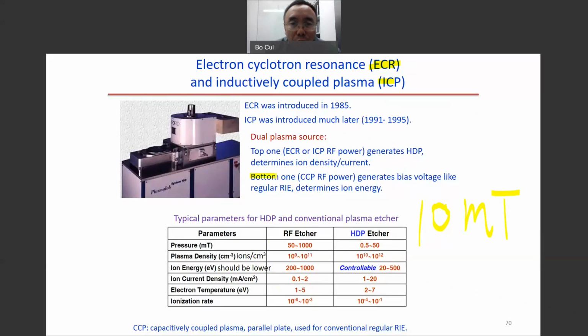This bottom electrode, so we have a bottom electrode. The top one is ICP, high density plasma. The bottom one is regular CCP, capacitively coupled plasma, parallel plate plasma. This one controls the ion energy. This one controls the ion number. So the ion energy can be much smaller. We have lower ion energy, as we have seen. We have higher selectivity and lower damage to the substrate. But for the regular RIE process, the ion energy usually has to be much higher. High density plasma has higher ion current, a little bit higher electron temperature. Ionization rate is also higher for the HDP plasma.